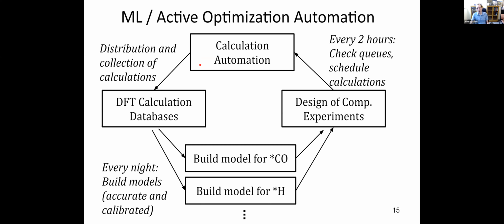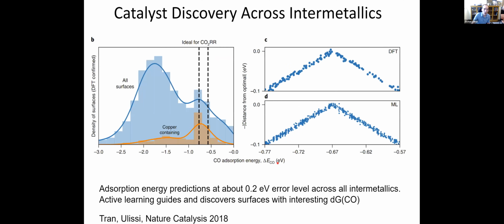This was something that was quite difficult 4 years ago, but has progressed a lot since then. And I think even in PyMatGen now, this has gotten quite straightforward. Christine and others have really cool workflows now to basically do similar things for CO and hydrogen for things like photocatalytic CO2 reduction, which is really exciting. So even in the past few years, we've seen a lot of maturity in this area. Okay, we applied the workflow. We found a lot of materials that were interesting. About half of the materials in this sort of window were copper containing. About half of them had no copper whatsoever. That was quite exciting.